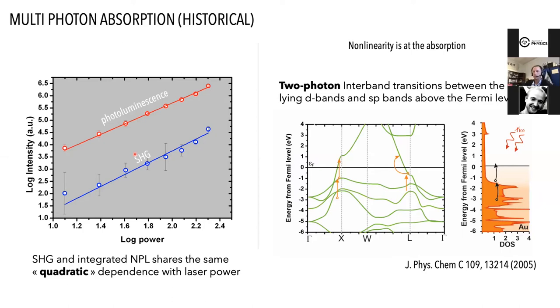So people have been discussing this quadratic dependence in terms of two photon absorption, in analogy with what we know with molecular excitation, where you also use highly intense laser in order to produce this two photon induced photoluminescence from single molecules, which also shows a quadratic dependence. And so by analogy, people were making this assumption that this photoluminescence is also coming from two photons, because we measure quadratic dependence with laser power.